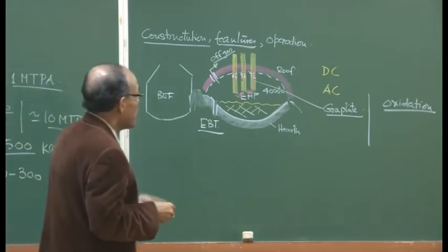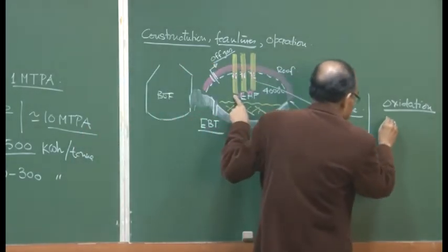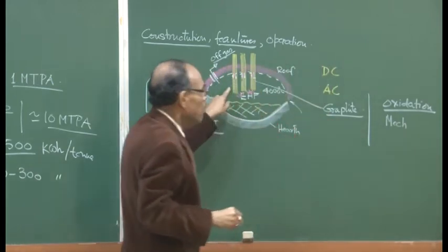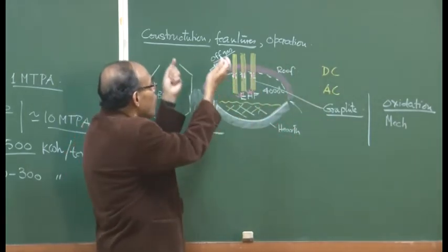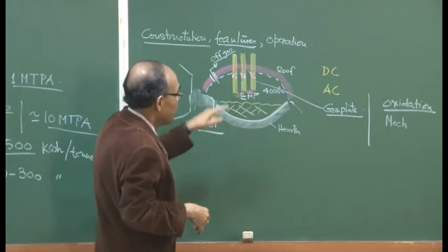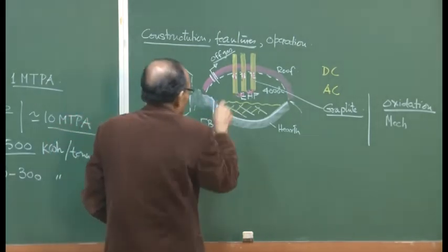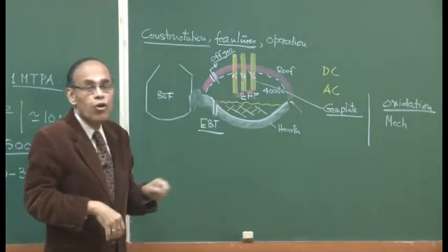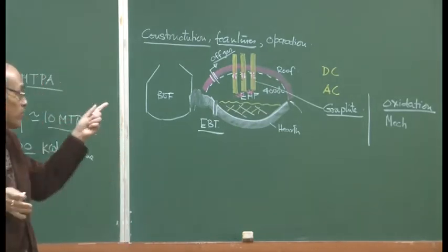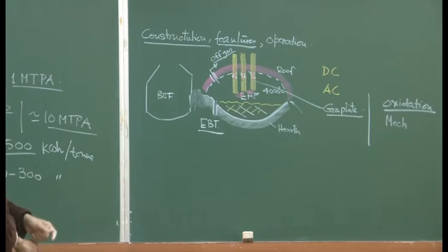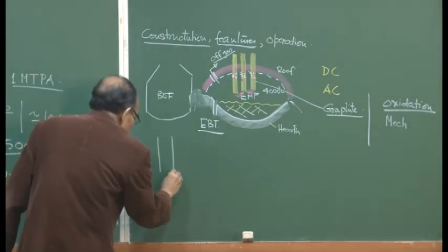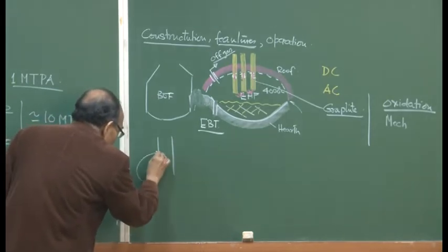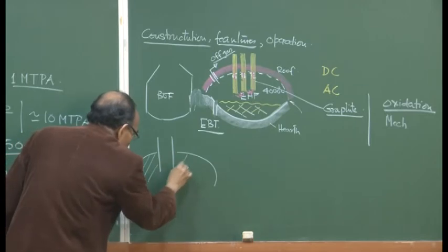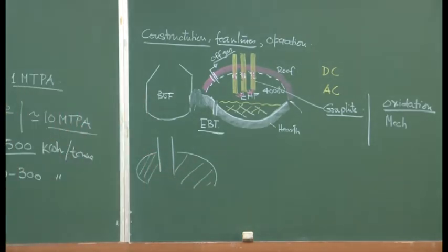So, these are expensive materials, with finite resistance, subject to oxidation and mechanical loss. Although carbon monoxide will be evolving, we have some oxygen partial pressure that can react. But most importantly, the part of the electrode which comes in contact with the slag, and particularly in electric arc furnace steel making, there is a practice called foamy slag. Basically what is done is, into the slag we introduce coke powder or small chunks of coke.